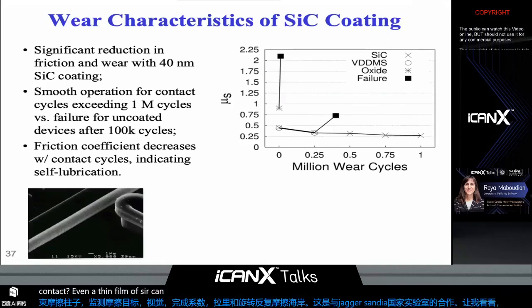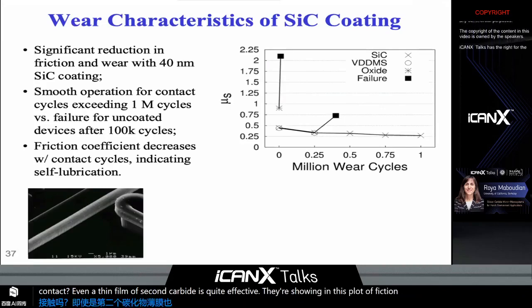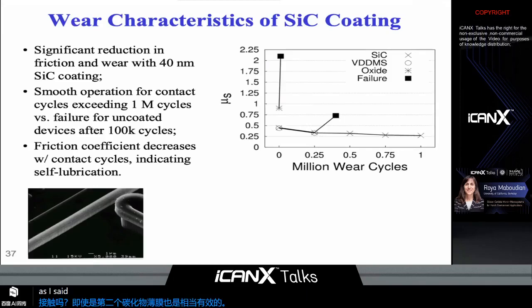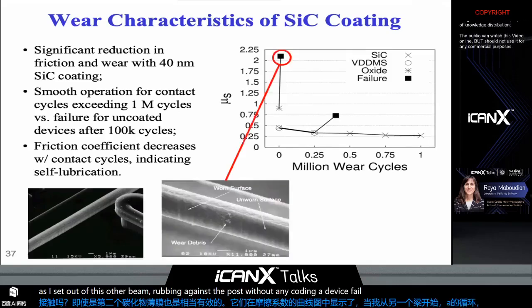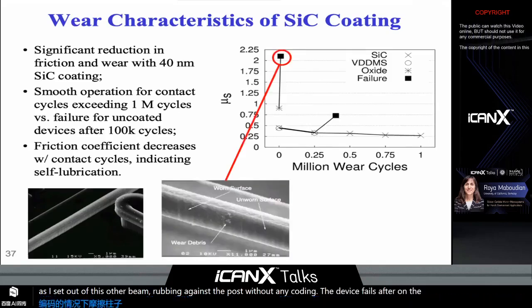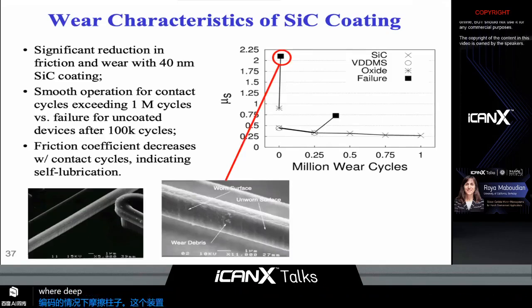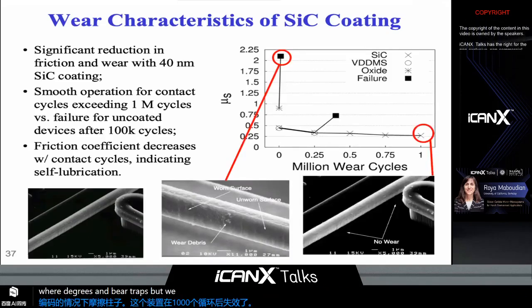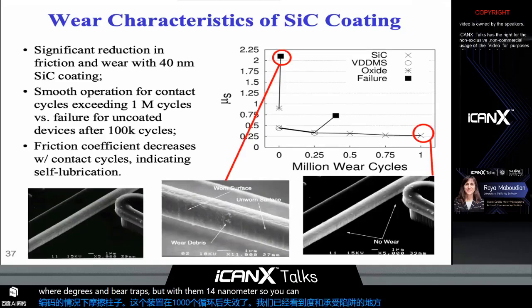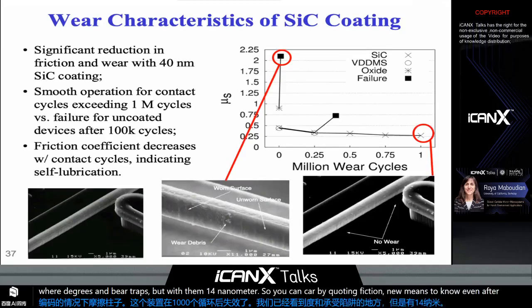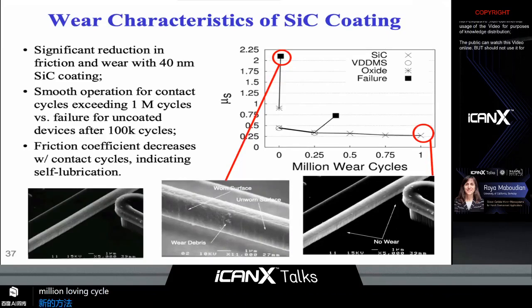What we see is that under repeated contact, even a thin film of silicon carbide is quite effective, as shown in this plot of friction coefficient versus wear cycle of a beam rubbing against the post. Without any coating, the device fails after 100,000 cycles, and we see wear debris and wear tracks. But with a 40 nanometer silicon carbide coating, friction remains low even after 1 million rubbing cycles, and we see no wear debris.